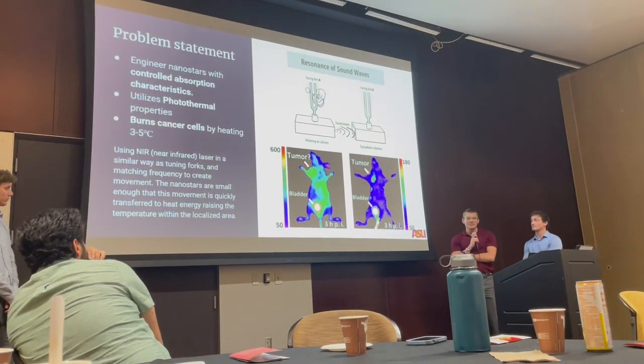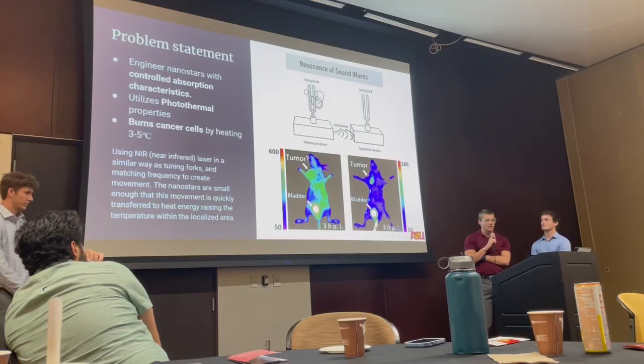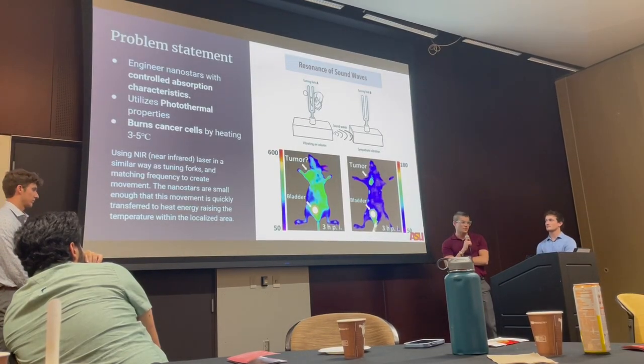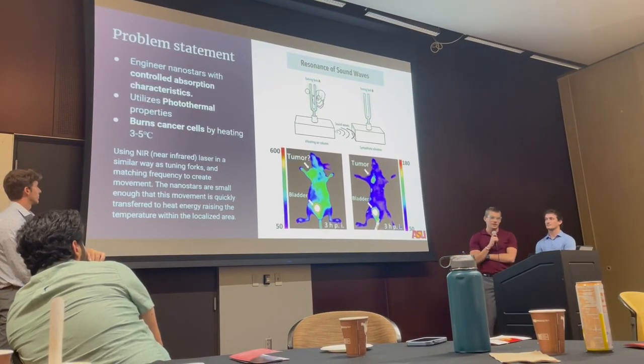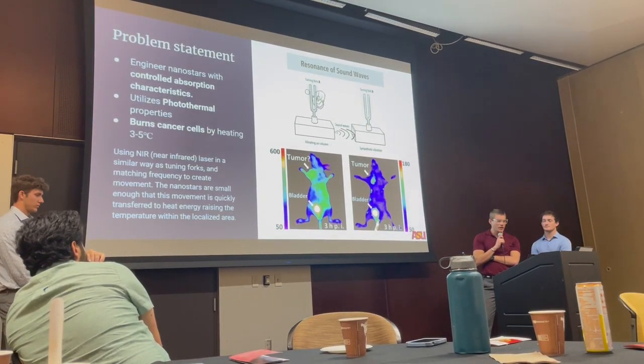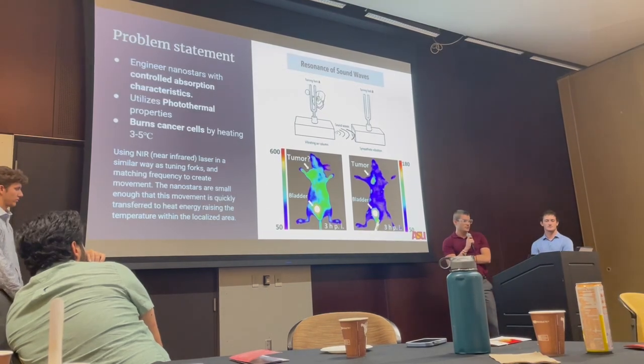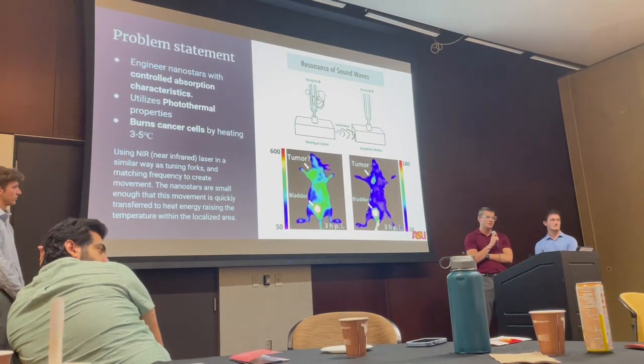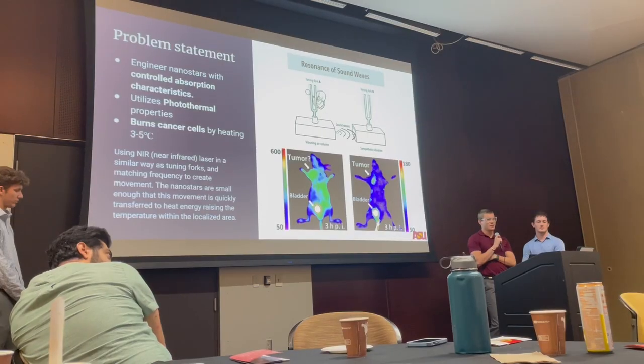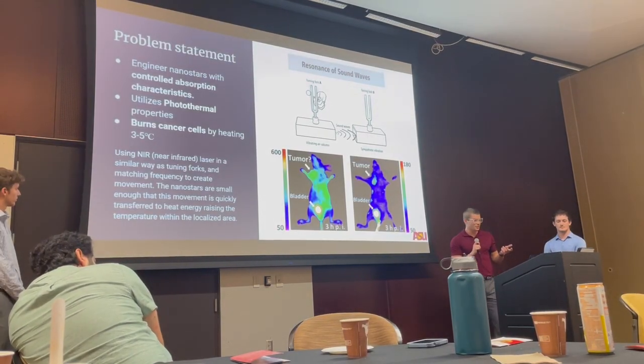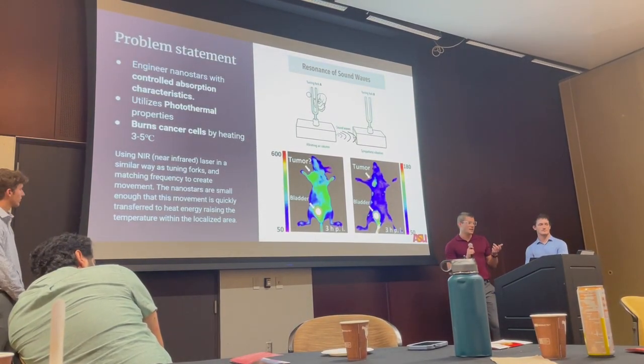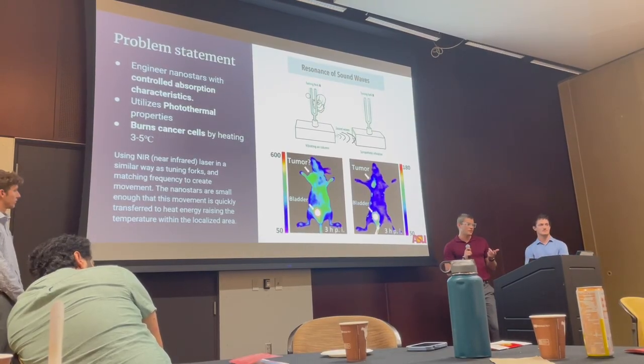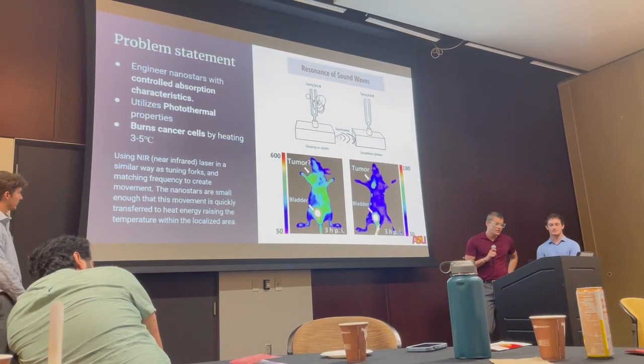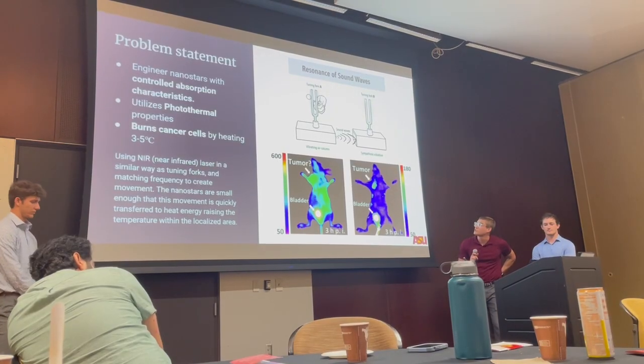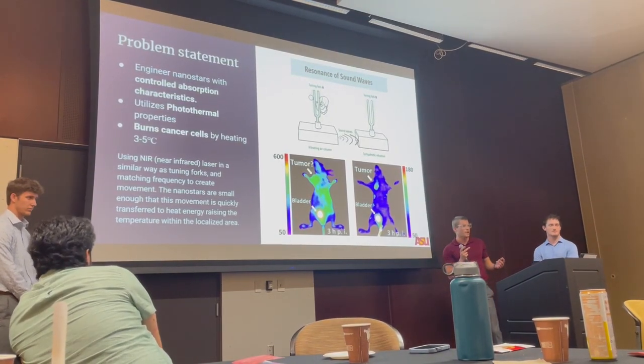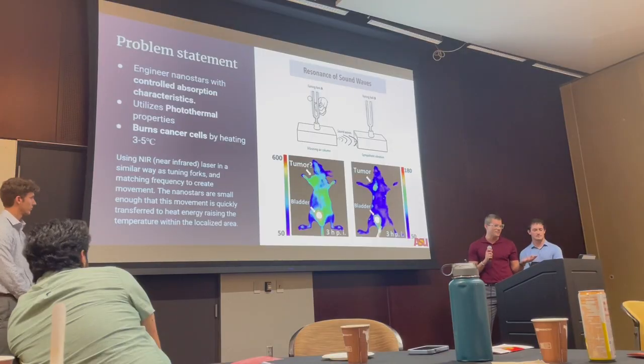Our main objective was to create unique nanostars with controllable absorption rates. Using a near-infrared laser that has the ability to pass through both bone and tissue, we use this to excite the nanoparticles that are placed within the tumor and then heat them. Using a photothermal effect, we can heat the gold nanoparticles up and therefore burn off the cancer cells. This is similar to if you were to use two tuning forks at the same frequency, and you play one, the other one will vibrate at the same frequency.